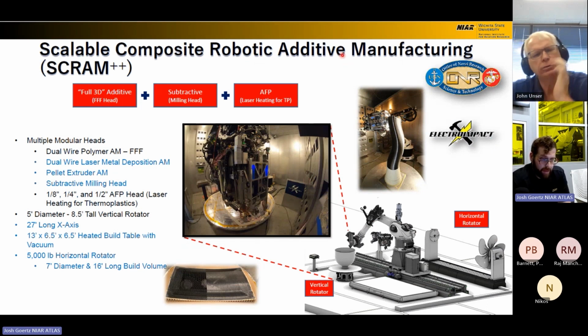And the next technology I'm going to be talking about is using the Electroimpact SCRAM machine, which basically combines a large number of 3D printing technologies as well as subtractive machining and automated fiber placement. So the particular capabilities of this machine is there's a single lane AFP head that can do 1/4 to half-inch wide thermoplastic, and then on that same head you actually have dual filament extruder 3D printing heads. So you can do a part like what's pictured here at the bottom, where you AFP a thermoplastic skin, and then you extrude on top of that a variable density core structure using the filament extruder, and then you can come back and encapsulate that with another thermoplastic AFP skin, so you can fully print a complete, rigid core structure.